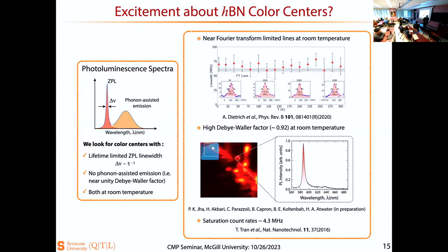So whenever we are looking for a candidate which can generate identical single photons, and this is a room temperature measure, we start with a good candidate which already has a high Debye-Waller factor, which is more than about, for this one, 0.92. So this is already a good candidate. So with a high Debye-Waller factor at room temperature, very regularly we will find 0.8, 0.9, something like that. The highest I have found is 0.92. This is the highest which I have seen at room temperature for a solid state. So these are really good features.